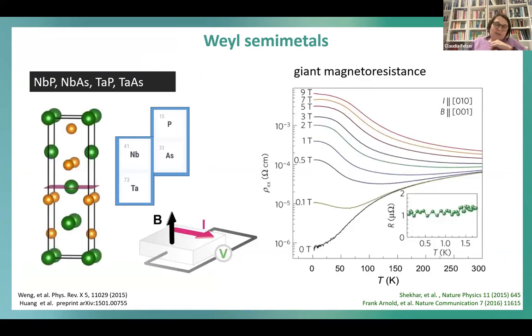If you make a good quality crystal, you always see a giant response, which means the properties as a function of magnetic field, electric field, light, and temperature are always extreme. Here you see, if you apply a magnetic field, you can significantly change the resistance from metallic to semiconductor-like. But all of these semimetals also have a plateau at the end.